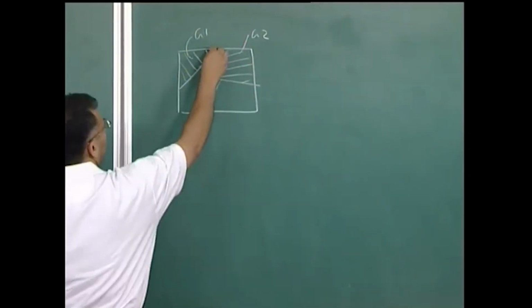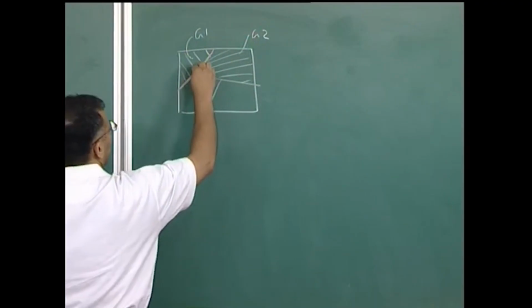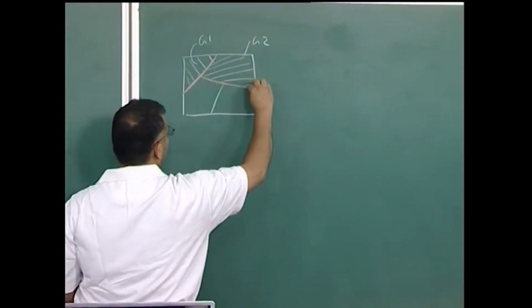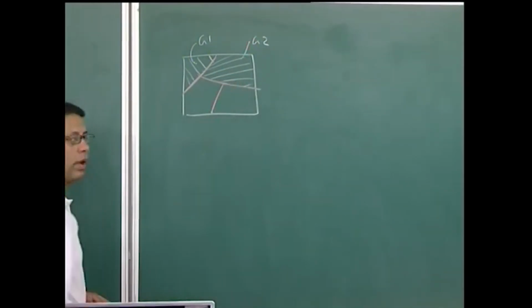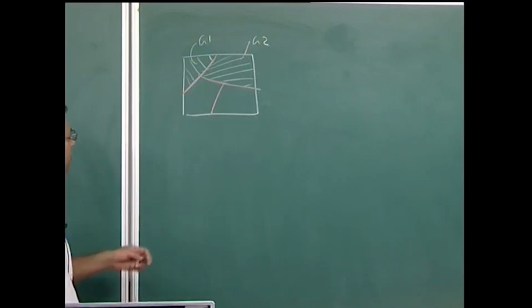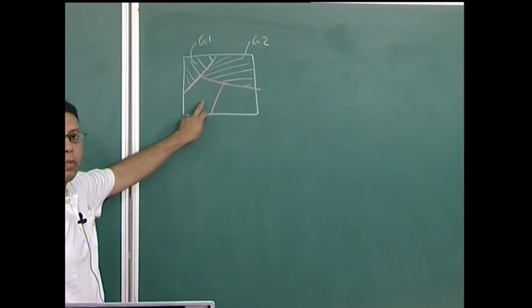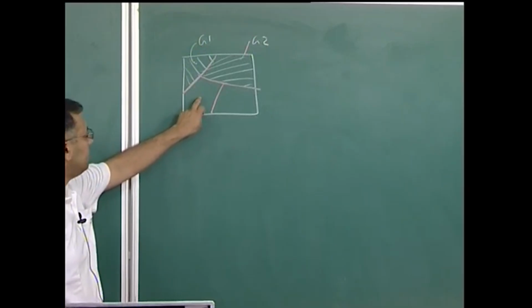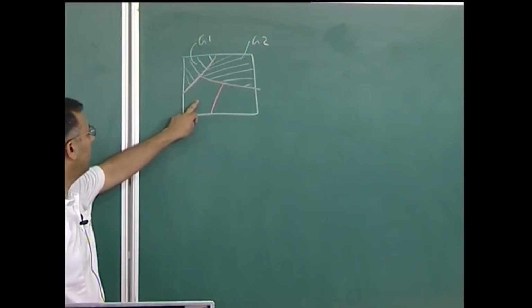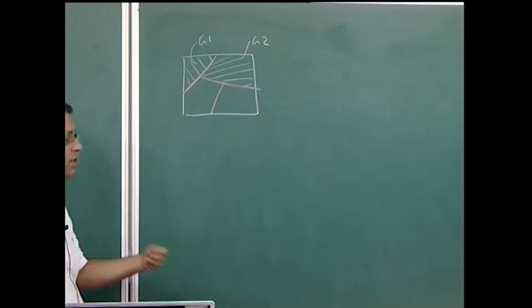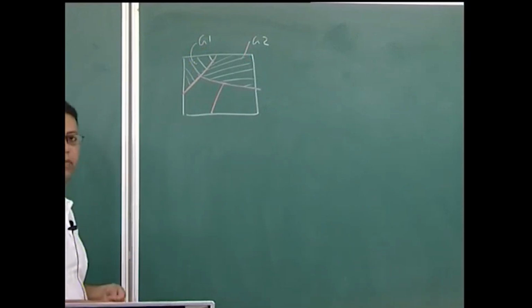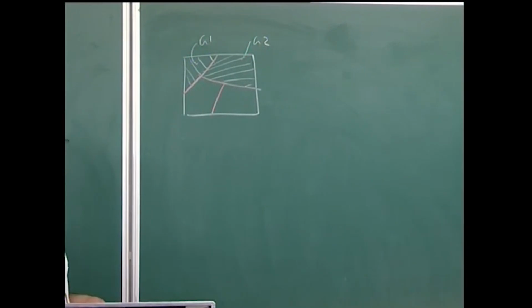Let me highlight the grain boundary by red lines. And we have already noted that grain boundaries are regions of lower coordination as compared to the bulk. So, suppose this were FCC copper crystal, then the grain would have a coordination number of 12, but the grain boundary would have something less than 12 and therefore, they are regions of extra free volume and lower density.